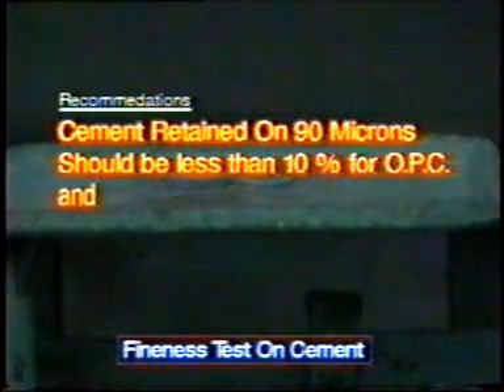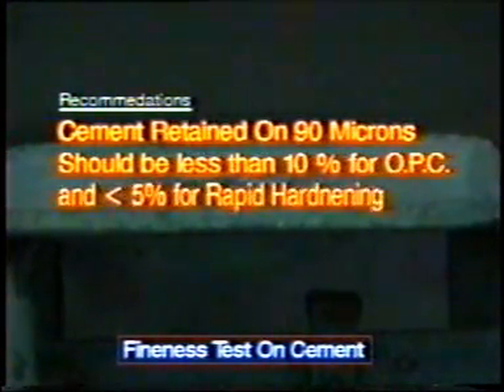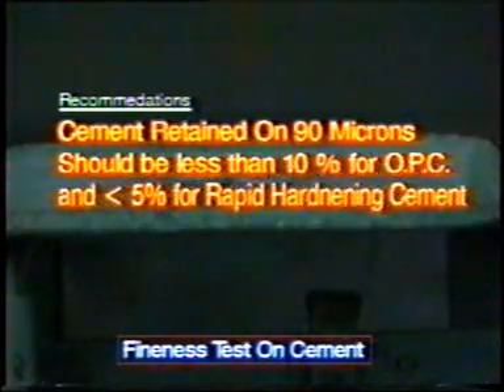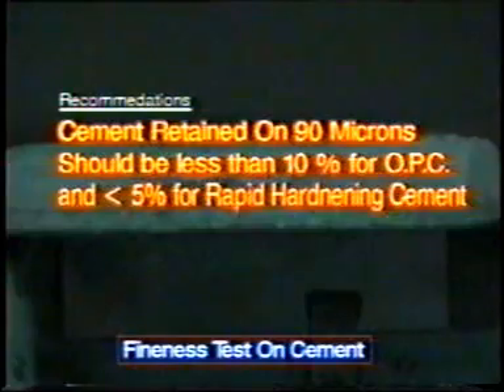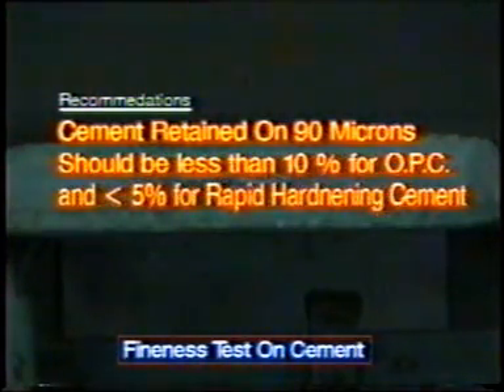of the cement taken. Recommendations of fineness of cement as per IS 269/1976: the residue left in the 90 micron sieve should be less than 10% for ordinary Portland cement. This should be less than 5% for rapid hardening cement.